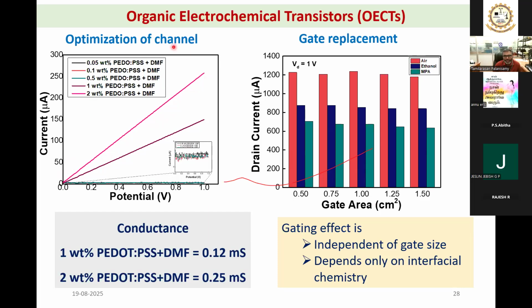But beyond this, it is not possible because we have to add DMF, and the standard concentration for PEDOT:PSS is 5% in water. So the remainder is DMF, the minimum DMF requirement. So with 2 weight percent, we got a higher conductivity, so we used it as a channel coating material. The conductance we have also calculated. It is 0.12 millisiemens for 1 weight percent, but for 2 weight percent, it is 0.25 millisiemens.